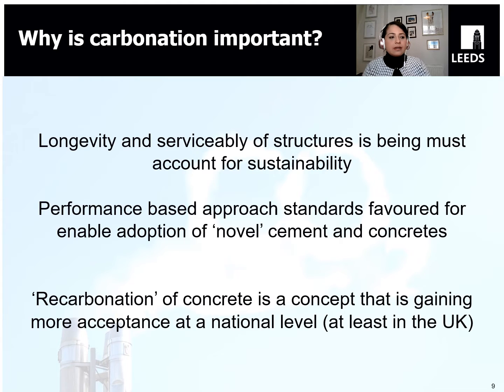And I will say concerning, because of course the concept of recarbonation is being accepted, thinking about carbon tax, potential statistics of air quality and pollutants. And the thing is, how can we truly determine the level of carbonation, or the ability of a given concrete to uptake CO2 during a lifetime of service? So I think the concept is really valid, but at the same time, I'm a little bit careful thinking about how any quantification can be done in a conservative way, so we don't overestimate perhaps the potential of carbonation in terms of CO2 savings in the longer term of cement and concrete.